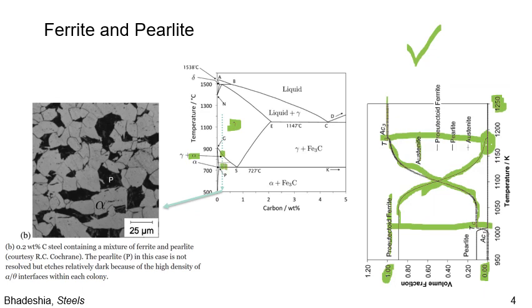And so now our remaining austenite, so we only have a little bit left here. I'm going to draw a square. We only have about 10% of our microstructure remaining as austenite here, because 90% of it has converted to ferrite. Here, I'll show over here. We have about 10% remaining austenite. But now, that remaining austenite converts to ferrite and carbide in a microstructure called pearlite, a constituent called pearlite.